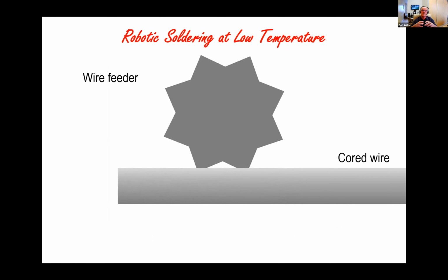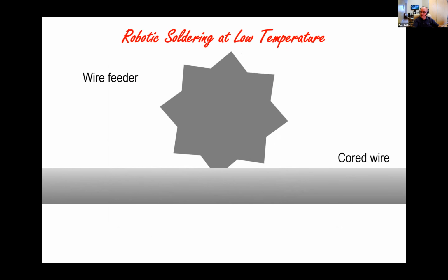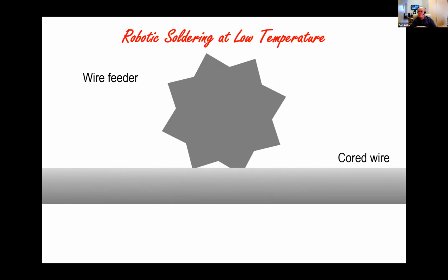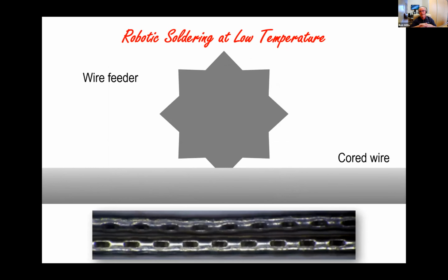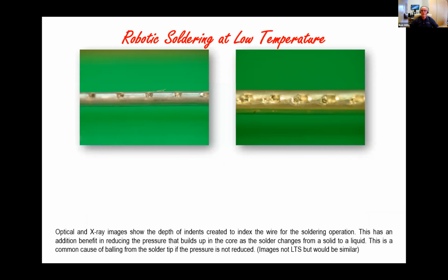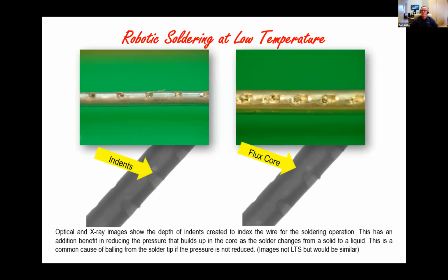So when we feed solder into the robotic system, whether it be laser or whether it be contact, we use a wheel which indents the wire. And you can see examples of indented wire at the bottom of this particular slide. And that's significant for two reasons. One, it feeds the wire, but more importantly, it reduces the pressure that builds up within the wire during the soldering operation.